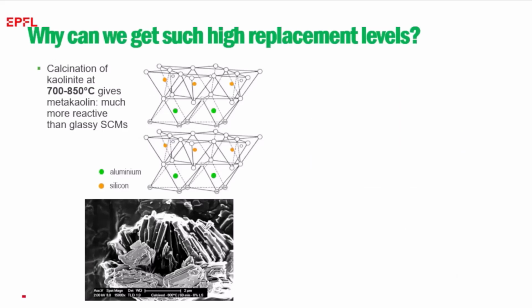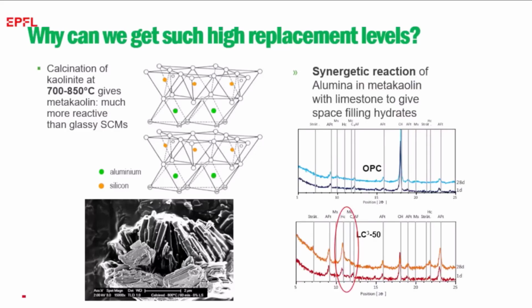It's because we use clays which contain some kaolin, and kaolin has this crystal structure like this. We have a layer of silicon atoms and a layer of alumina atoms. When this is calcined in the range 700 to 850, this structure gets disrupted, and the silica is available to react in the conventional pozzolanic reaction, but then the alumina can react with the limestone.